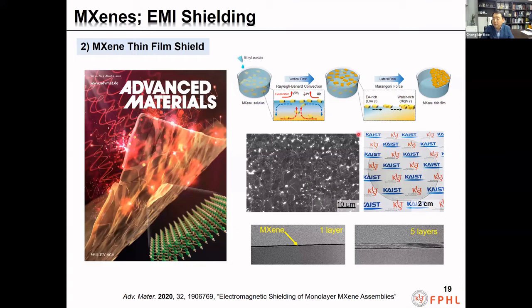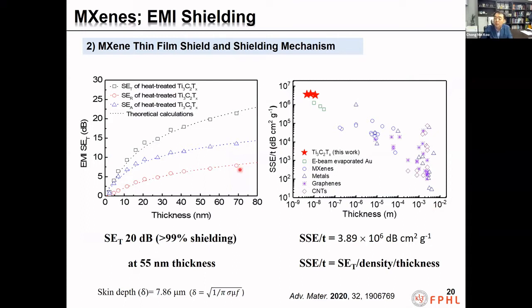And then the assembled monolayer film is transferred to the substrate, and film thickness is controlled by the multiple stacking of the assembled monolayer film. We systematically studied the shielding property of the thickness controlled assembled MXene thin films. The figure shows the total shielding effectiveness SET, shielding effectiveness by reflection SER, and shielding effectiveness by absorption SEA of assembled films. SET, SER, and SEA increase with the increase in thickness. The symbol is from experimental data and the dotted line is from the theoretical calculation. The experimental data agree well with the theoretical calculation considering the multiple reflection effect.